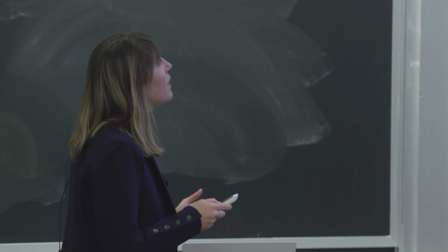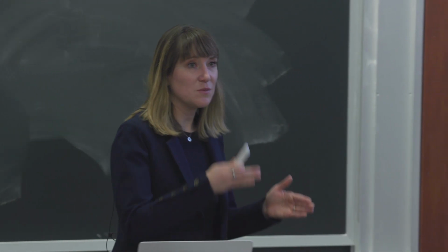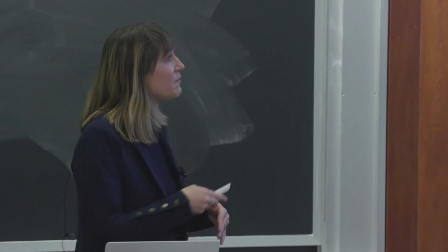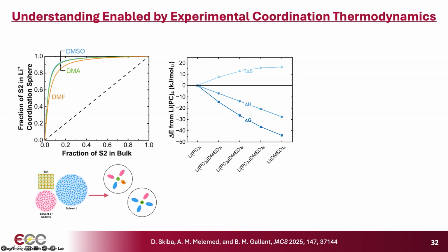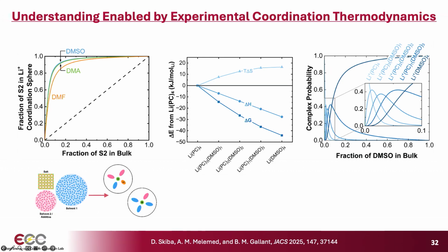We can also map out the progressive driving forces as we sequentially displace 1, 2, 3, 4 of the weaker solvent with a stronger solvent. And we can also map out the distribution of the complexes as a function of the strong solvent in the bulk. So we can really get experimentally based microscopic insights.